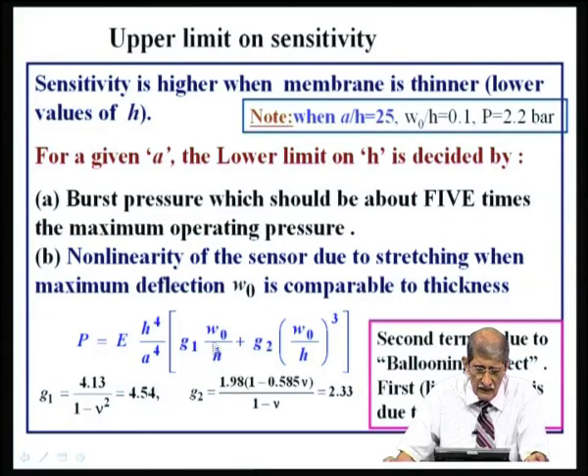Now, if I keep on increasing the pressure, the deflection will become more and more. At a certain point, the deflection will become comparable to the thickness. For example, if the deflection is 0.1 times the thickness, that is, if h is 10 microns, if the deflection is 1 micron, you can see this second term will become comparable to this first term, about 10% of that, that is at the pressure of 2.2 bar.